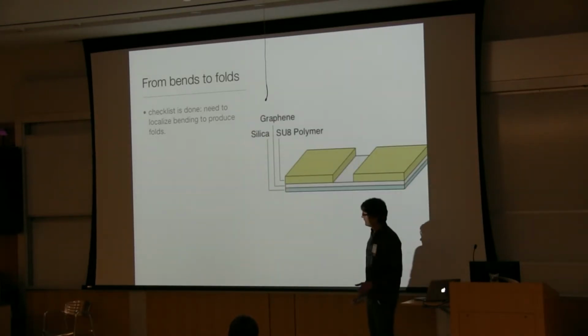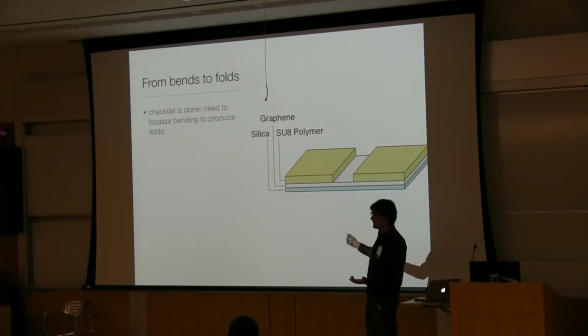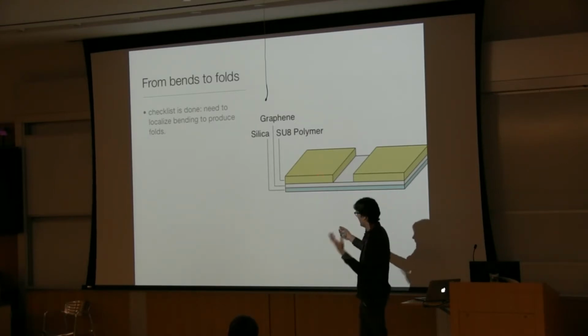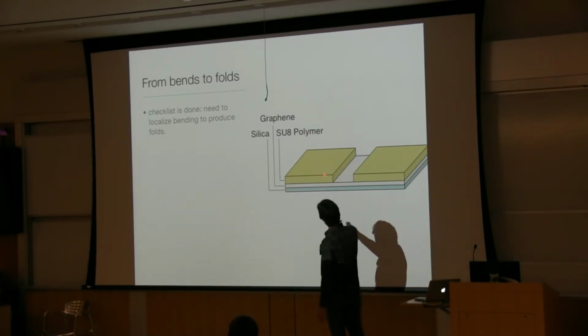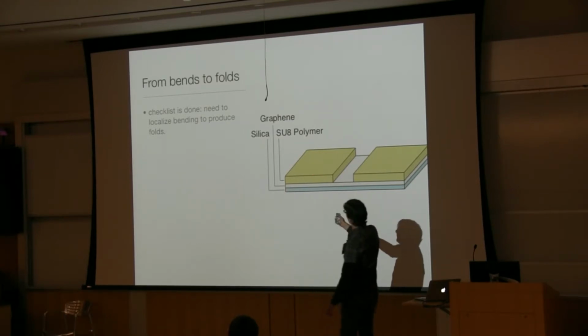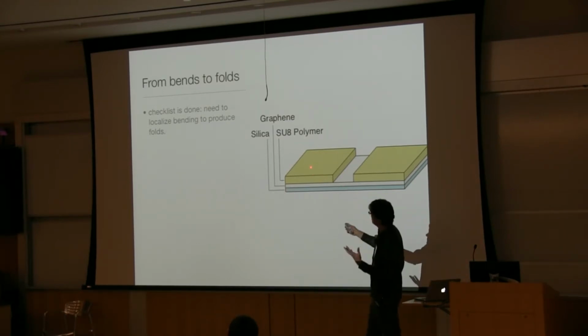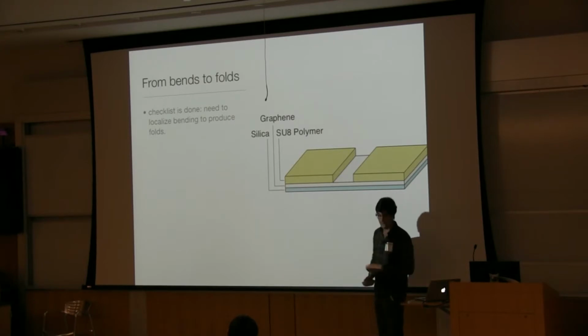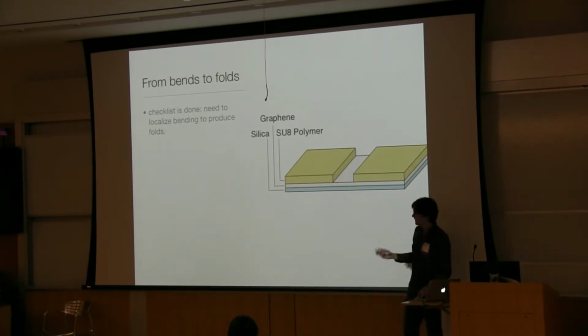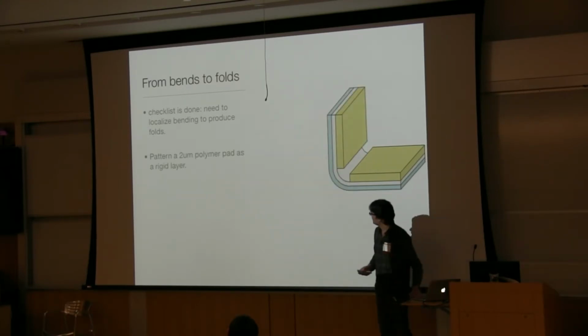As Robert said, one of the key ideas is you just vary the flexibility between the two layers to make a panel that's much stiffer than the joint. So what we did is we patterned enormously thick layers of polymer. They're 2 microns, about 1 million times thicker than the graphene glass bimorph. And as a consequence, they're much more stiff. And so the bimorph can't bend here, but it can bend here. And when you release it, the device will, in principle, fold up.